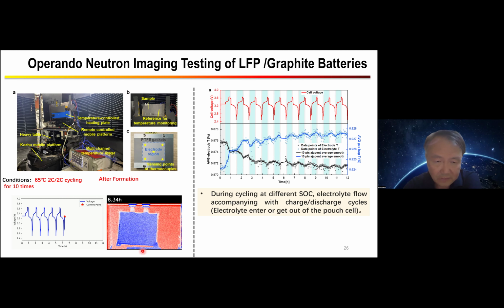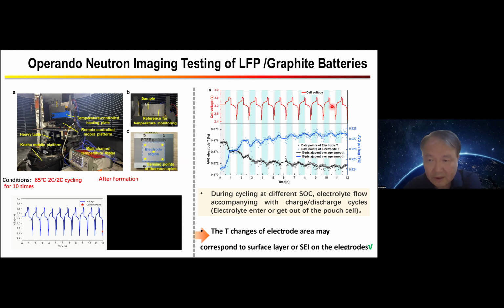If you can see, this kind of electrolyte movement during the charging or discharging process is also very important for the evolution of the battery states, and it causes some redistribution of the electrolyte in the pore structure, and also causes some density change. We believe that it may be due to some SEI changes - we will show some more direct evidence later.